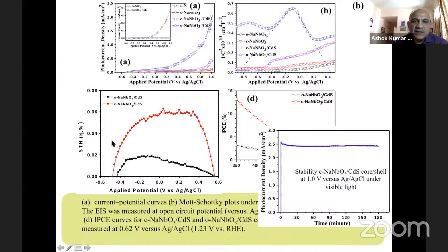Same thing, you can convert these numbers into solar to hydrogen ratio. And the solar to hydrogen ratio for the one which forms in the cubic crystal system, the cubic crystal system has actually the octahedral facets. Okay, that is the two facets, 111 and the 100. And that one gives rise to a higher, around 6% efficiency of the solar to hydrogen plot. Okay, whereas the other one, which is in the orthorhombic crystal system, which is basically due to the cube-like morphology of the nanocrystals of sodium niobate, that has a lower number for this STH, which is the solar to hydrogen